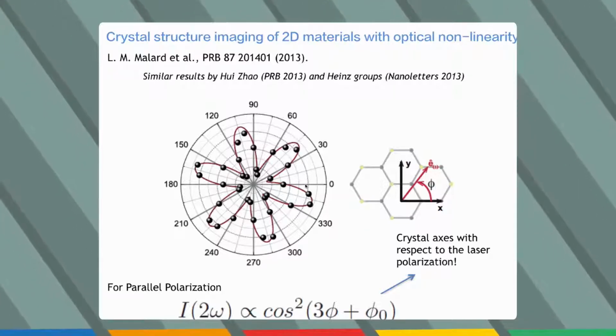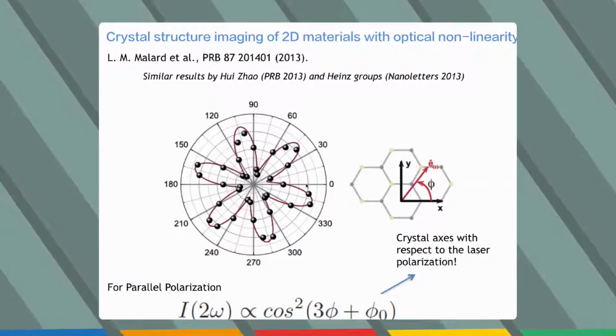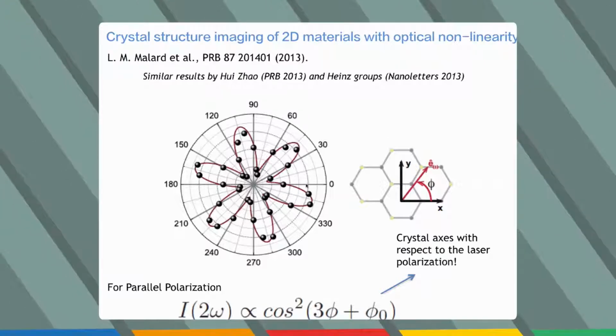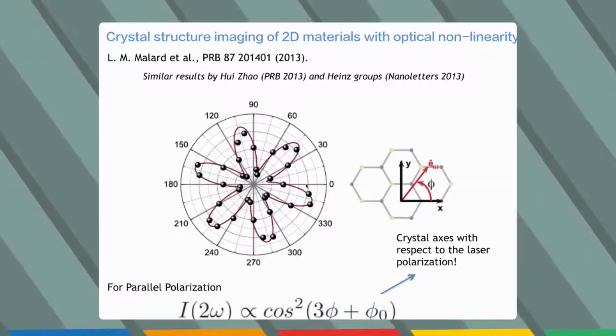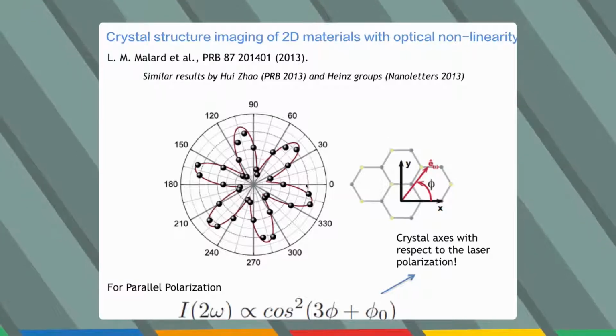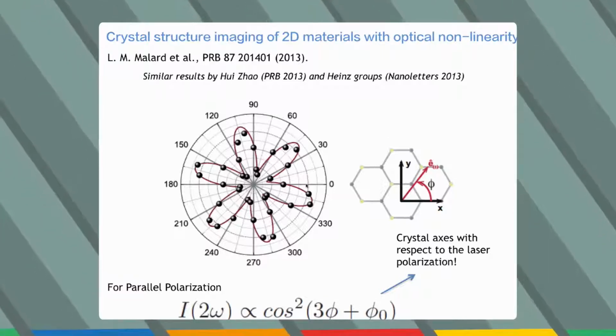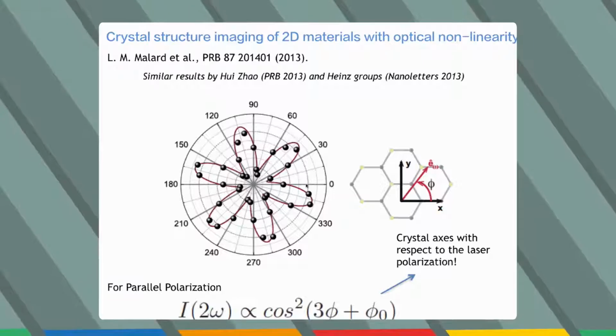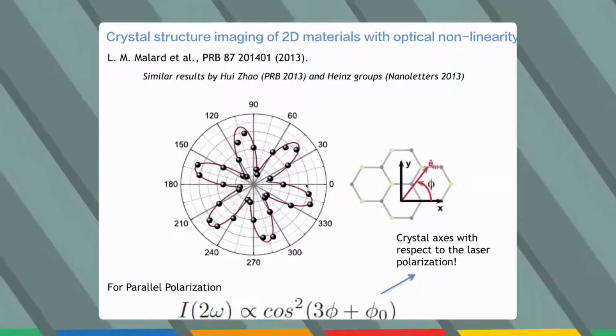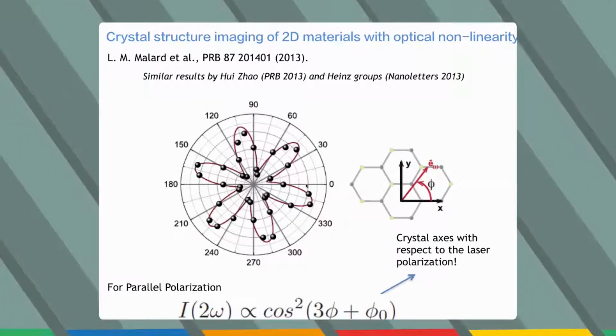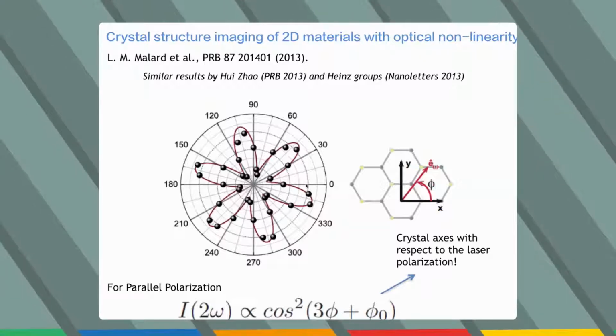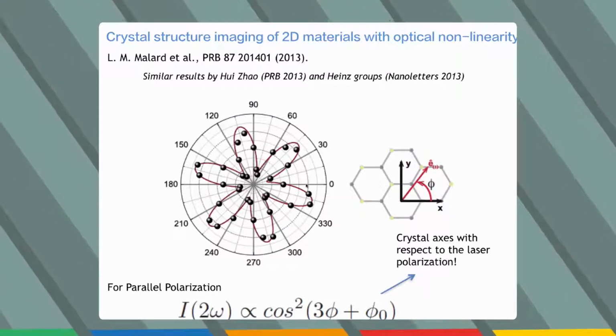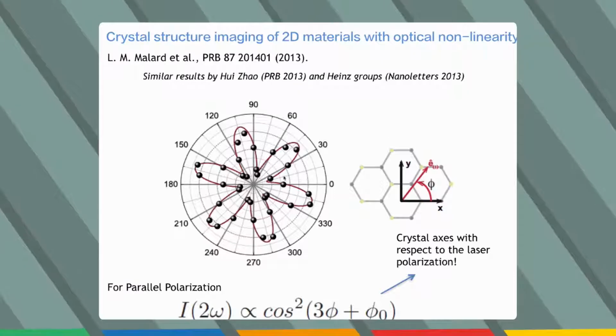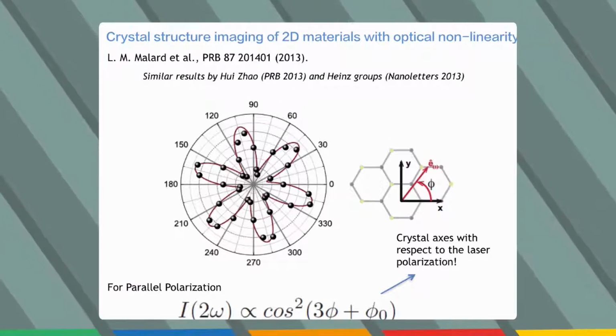Nowadays, this is being used for creating these twisted layers of different 2D materials. So we want to put materials on top of each other with a determined crystal orientation between them. So we can do second harmonic on one sample, determine the crystal orientation, do the same on the other one, and then rotate one with respect to the other.